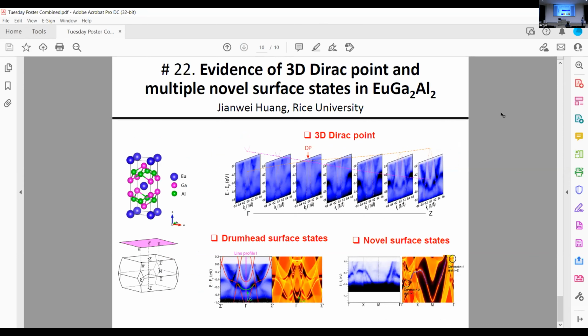My poster is about revealing multiple topological bands in the europium gallium-2 aluminum material. This material has a body-centered tetragonal crystal structure, which is the same as the more famous 122 iron-based superconductors. We find that there is a 3-dimensional bulk Dirac point at the Fermi level, which is protected by the C4v axis. We also find these so-called drumhead surface states inside this bulk Dirac nodal loop, and this bulk Dirac nodal loop is protected by the 001 mirror symmetry.